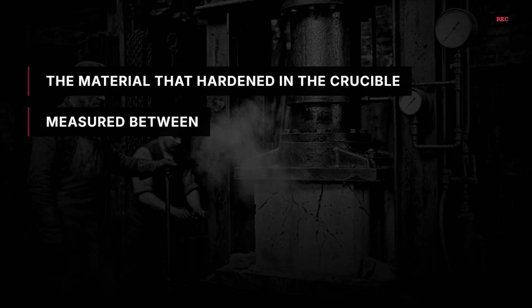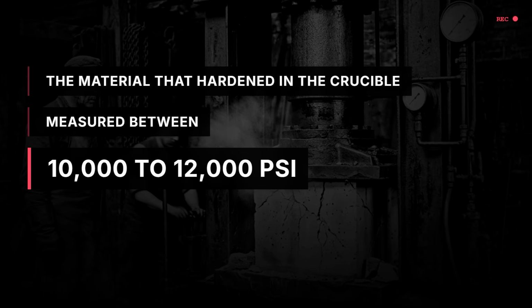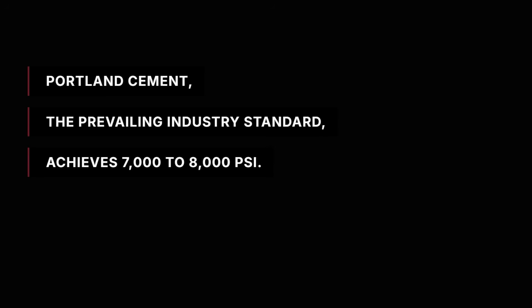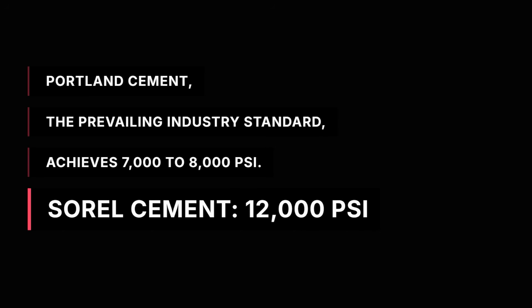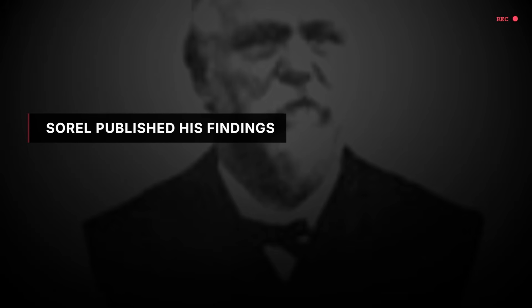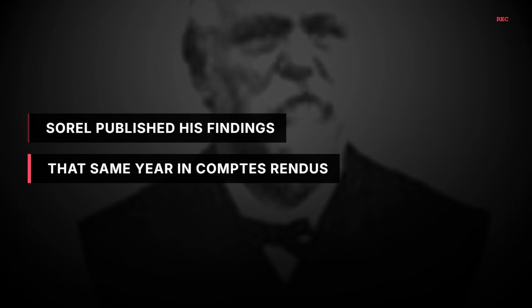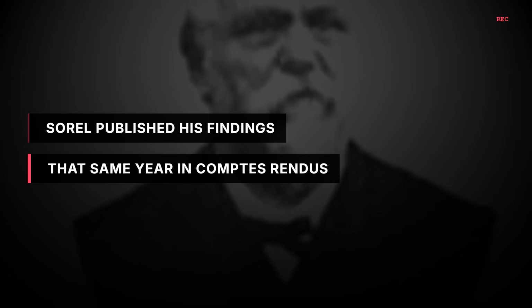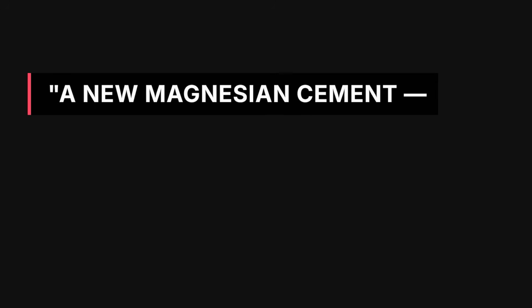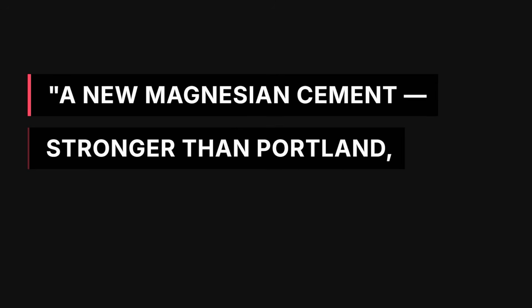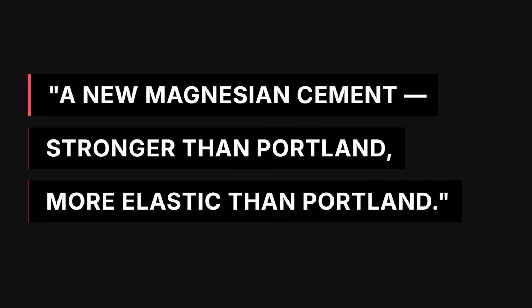The material that hardened in the crucible measured between 10,000 and 12,000 pounds per square inch in compressive strength. Portland cement, the prevailing industry standard, achieves 7,000 to 8,000. Sorel published his findings that same year in Comptes Rendus under the translated title, A New Magnesian Cement, Stronger than Portland, More Elastic than Portland.